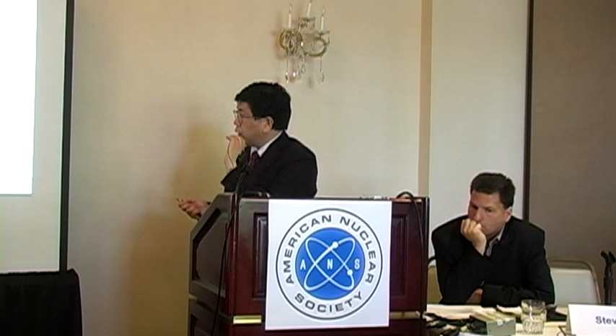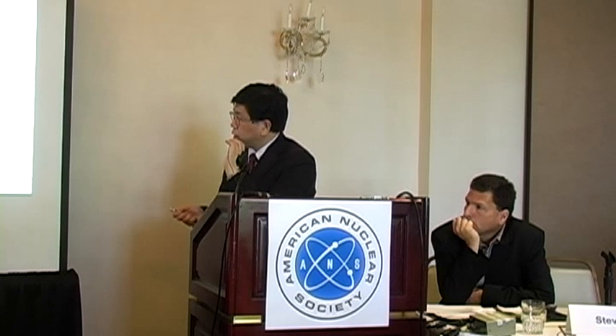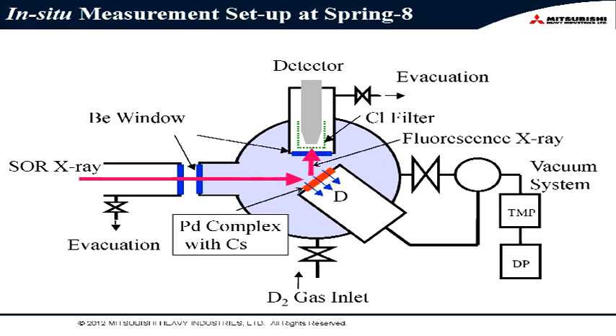We use the synchrotron X-ray here, we put the sample here, and the detector is here. So we can measure with this apparatus using XRF, X-ray fluorescence spectrometry. XRF is a very established analysis method, so we use this facility. This figure shows the in-situ measurement setup at SPring-8. As I said, the synchrotron X-ray comes here, and here we have a palladium complex with cesium, and this chamber is filled with D2 gas, and the D2 gas permeates through this. And we can get the fluorescence X-ray from the surface, and we have a detector here.